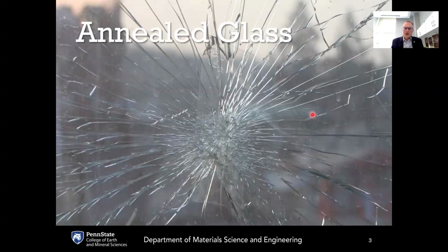This is kind of the boundary between where the glass has more liquid-like properties, more like a supercooled liquid, versus more solid-like elastic types of properties. So annealing takes place right at the boundary between those two. And the glass is held there for tens of minutes, all the way through hours. For large glass pieces, the annealing could even go on for months.